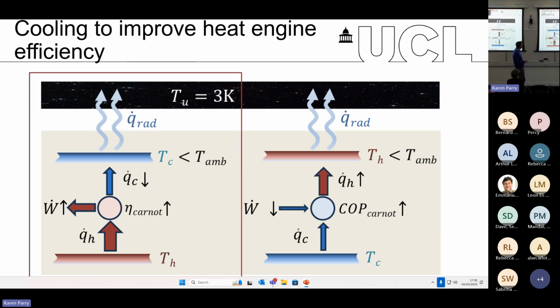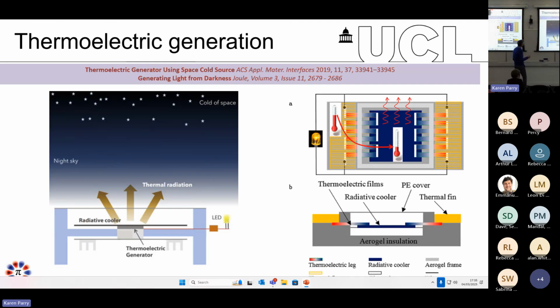Just to give you a couple of quick examples of this. A prototypical example in the field is thermoelectric generation. Thermoelectric generation leverages the Seebeck effect. Basically, it translates temperature gradients into voltage, and so useful electricity. In traditional thermoelectric materials, it is usually the hot side that's exposed to the heat source, and the system works by heating up the hot side, whereas the cold side is usually at ambient temperature or slightly above the ambient temperature, 5 to 10 degrees above the ambient temperature.